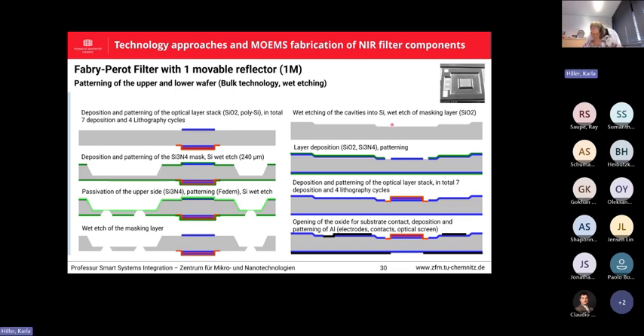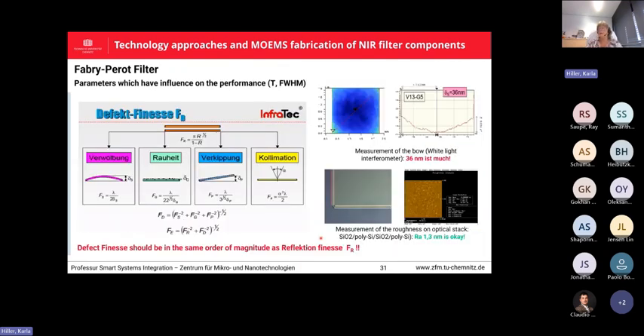And if we look at the lower wafer, also silicon in this case, we do etching steps to establish both the optical cavity, but also the electrostatic gap. This can be the same, but also can be different. Then again, we do the deposition of this optical layer stack. We protect the outer side to be able to etch the materials selectively and keep a thermal oxide as isolation layer and as bonding surface. And finally, we apply metal on the front side, creating the electrodes, and also on the back side to provide an optical screen. And then these two wafers are bonded together by silicon direct bonding.